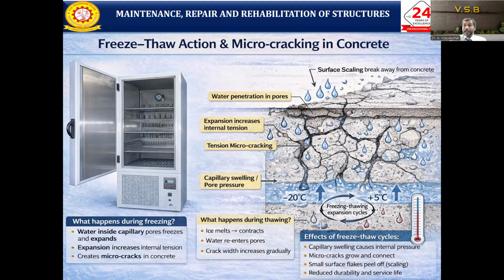Expansion will increase. Internal tension will be created in the concrete members, and because of the internal tension, cracks form. Other surfaces also get tension micro-cracking. Later, the micro-cracks have a chance to widen. Through this widening, again water gets into the micro-cracks, and the cracks increase. Once micro-cracking is produced, water penetrates, and definitely capillary swelling will happen. Pore pressure builds up in all the places the water can penetrate.